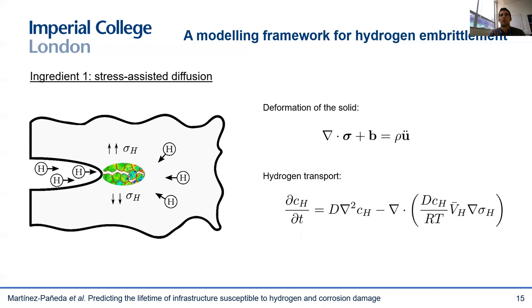We need to solve an equation for the strain and stress state — the standard balance of linear momentum — and we need to solve an equation for the transport of hydrogen within the crystal lattice. The hydrogen diffusion equation is essentially an extended version of Fick's law, and you can immediately see the coupling with the mechanical problem through the hydrostatic stress.